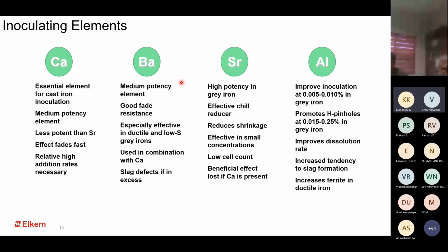In fact, aluminium inoculant finds its maximum application in heavy section ferritic ductile iron castings, because it has a very good tendency to promote ferrite. So most of the in-mold inoculation that you would see, the inserts and those blocks that we add into the heavy section castings, especially windmill castings, are in most cases aluminium-based inoculants.